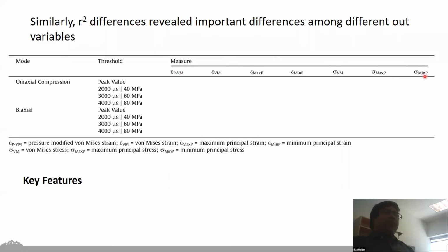In the columns are some of our different measures. Sigma indicates stress, while epsilon indicates strain. We looked at the von Mises, maximum principal, and minimum principal criteria, as well as the pressure modified von Mises strain. In the rows, I'm going to show you the R-squared values associated with the peak of the measure, as well as strained volume measurements using one of 3 different threshold values. Finally, I'm going to show you the results for both the uniaxial compression case, as well as the biaxial loading case.